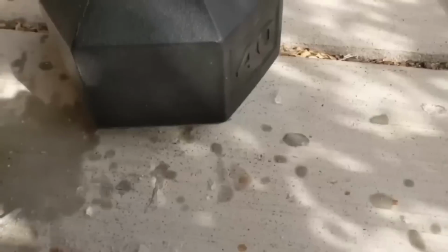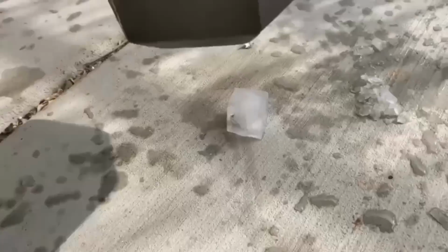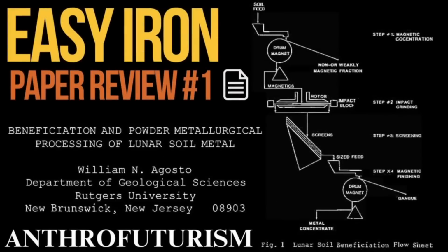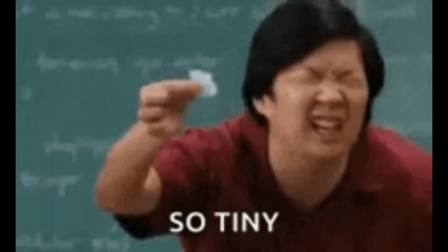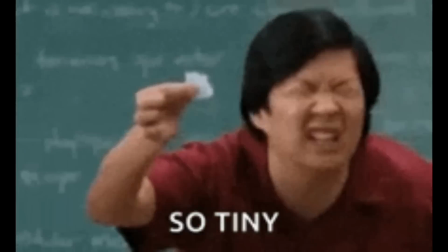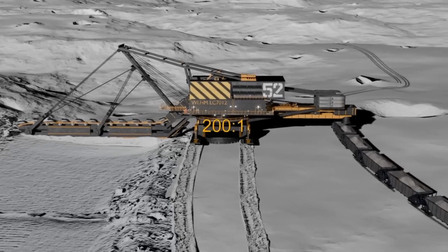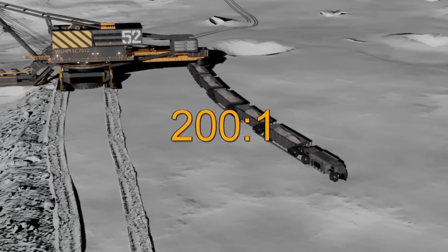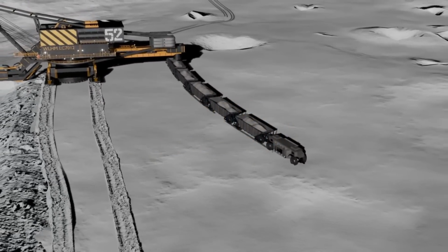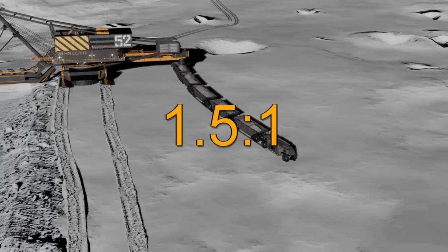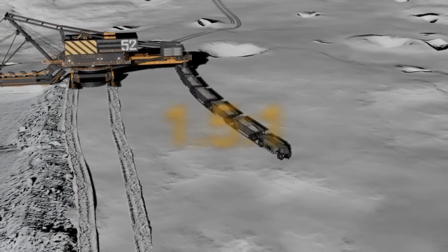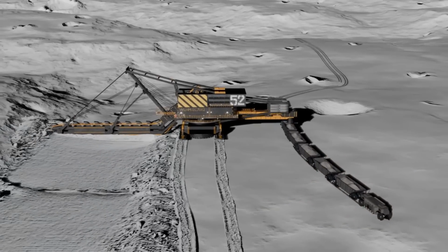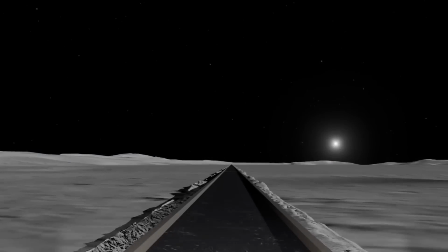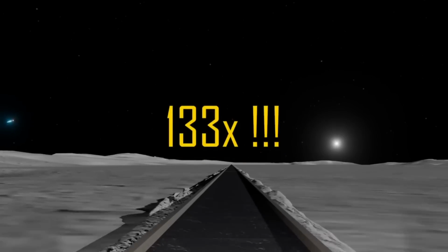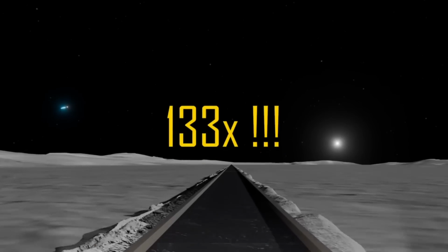Even more, non-mineralized free iron, the kind we'd be collecting with that cheapest of iron collecting methods, the magnet beneficiation technique proposed by William Agosto in 1981, makes up only 0.5% of the regolith's mass. So we'd need to process 200 tons of regolith for a single ton of iron. For a single ton of sintered or cast regolith, we'd only need to process something like 1.5 tons of regolith. Assuming all else is the same, to compete with the sintered regolith, collecting iron would need to be roughly 133 times cheaper than collecting and melting regolith.